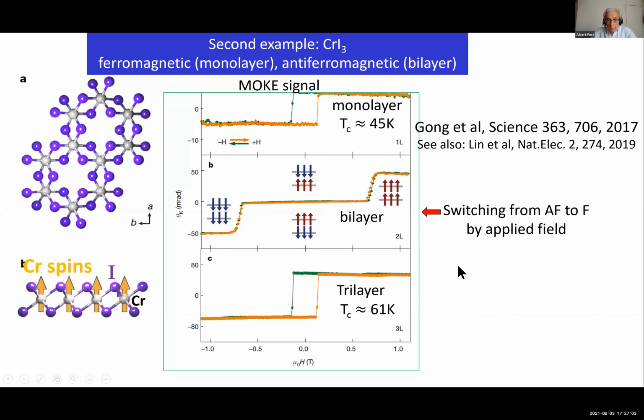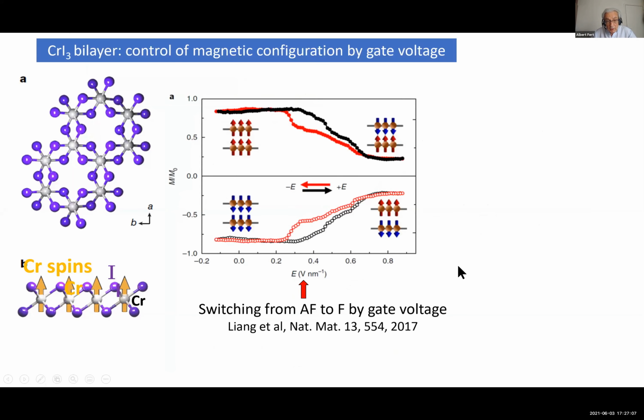So this is an example of CrI3. And in fact, for CrI3, this is a good example of how the magnetic property can be manipulated by applying an electric field. A very small electric field, corresponding to a small gate voltage, for example, on the system. You can see for CrI3 how, by applying a vertical electric field, one can go from ferromagnetic alignment to antiferromagnetic, or in the opposite direction. So the magnetic property can be easily manipulated by an electric field. Its manipulation is easier in 2D materials than in 3D magnetic materials.